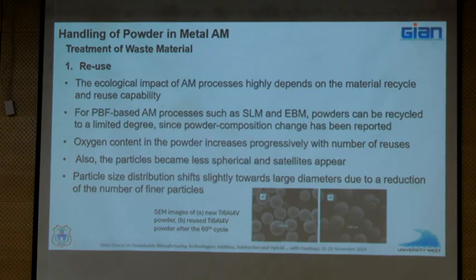I am showing you here an image from some of our work where we have used Ti6-4 almost 70 times, right? Here I am showing you only the morphology. You see, this is how you start, because the supplier is recommending spherical powder, no satellites. Here the sphericity is retained. I apologize for this bad micrograph, but you see some satellites coming up on these powders, but it can still be used. It of course has slightly higher oxygen content in the powder, right?